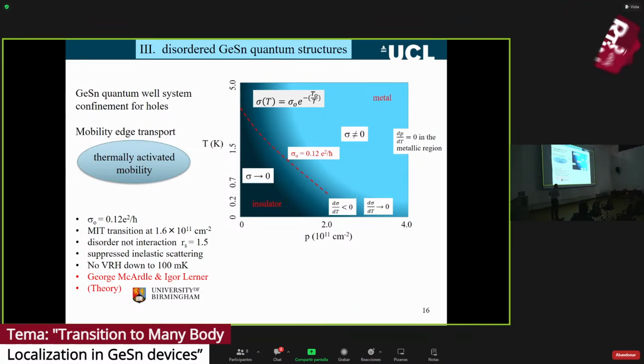We've got this dotted red line here, which shows where the system comes down to the minimum metallic conductivity predicted by Mott. At the minimum metallic conductivity, the elastic mean free path can't be shorter than the distance between the atoms in the lattice. So that's originally where it came from. Also, sigma tends to 0 down here. Once we've gone through this region, the conductivity tends to 0. That's one of the signatures we're looking for with this many-body localization state, but it hasn't come through this hopping conductivity.